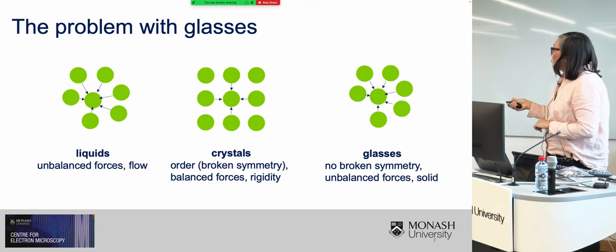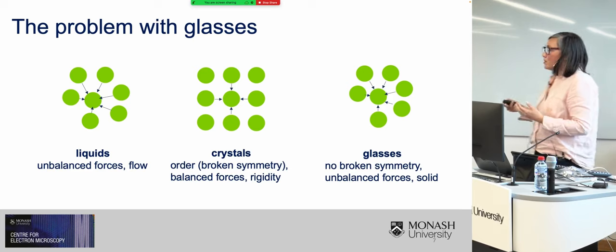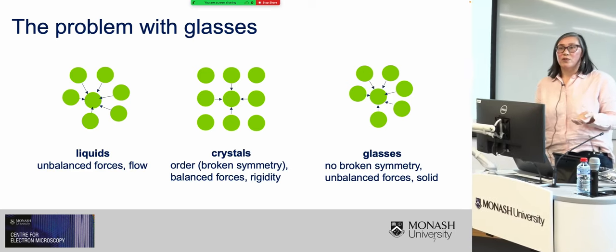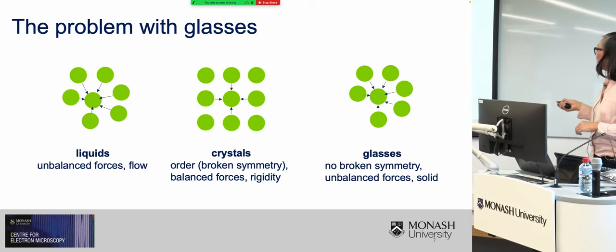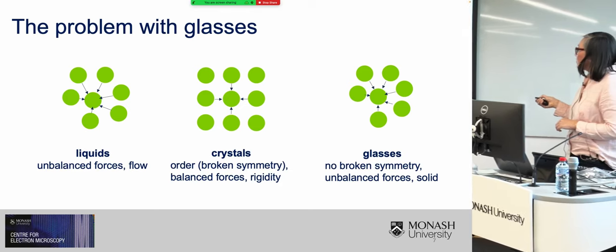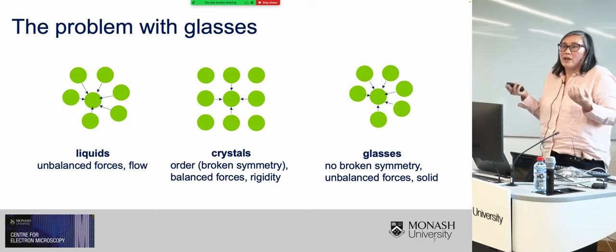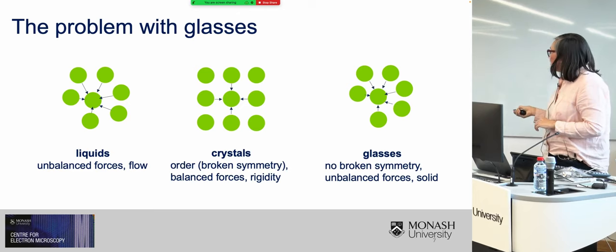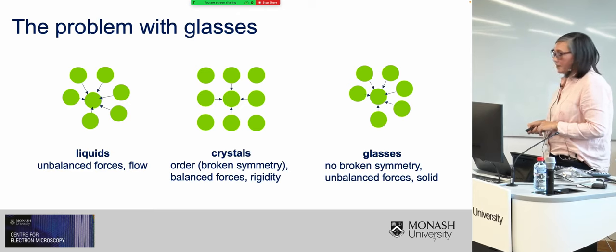Now, if you cool down your liquid really quickly, so if you quench your system, then you can avoid the transformation to the crystalline phase and you obtain a glass. Now, the glass has no apparent order, no apparent broken symmetry, and yet the forces on any given particle are still unbalanced. And strangely enough, it has solidified.